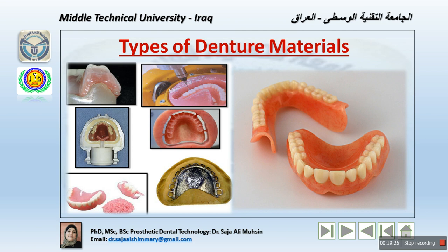So the process of polymerization between the atoms on the monomers, the forming of free radicals and their reunion again to polymerize, will really produce a semi-perfect denture base material in terms of resin, with minimal porosity within the framework. Now, polymerization should be carried out slowly to prevent gaseous porosity and under pressure to prevent contraction porosity.